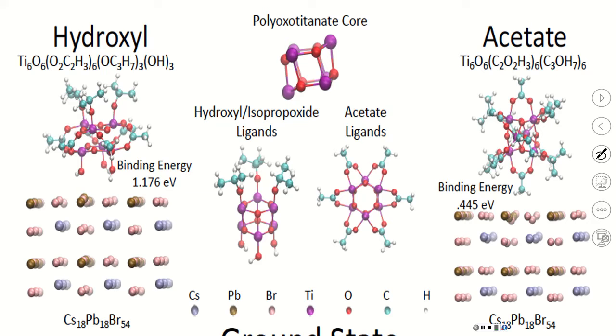But if we go to the idea of using a cluster instead of periodic, instead of an infinitely large slab, then the question is stoichiometry. So titanium, one titanium per two oxygens. But if you cut the surface, here it's like six titanium and six oxygen. It's non-stoichiometric. So one needs either to put oxygens aside and one needs to avoid trap states, same as we always do for quantum dots. So one needs to design ligands that will allow this cluster to mimic the gap of the periodic bulk or the cluster.